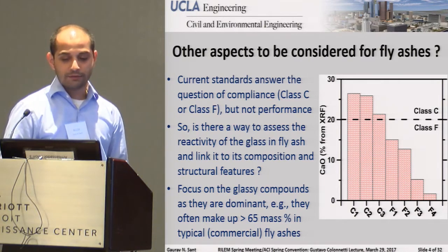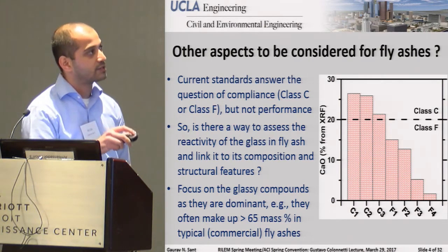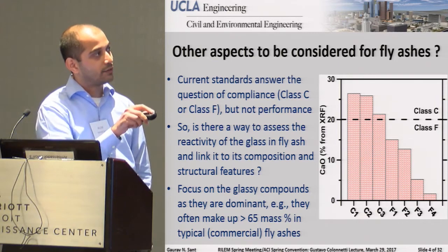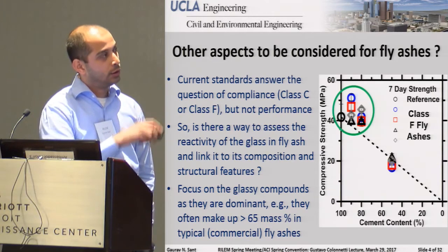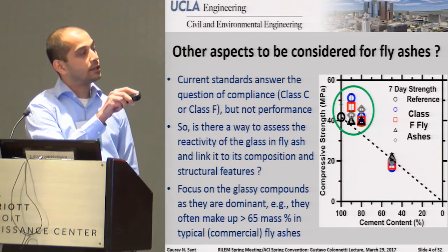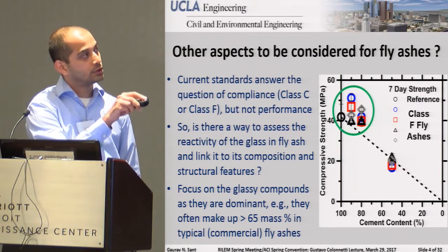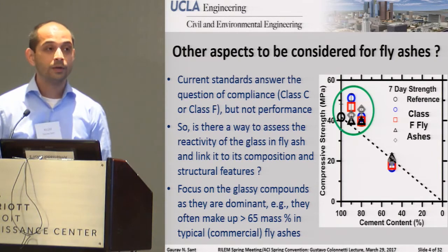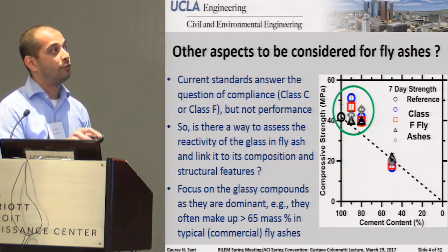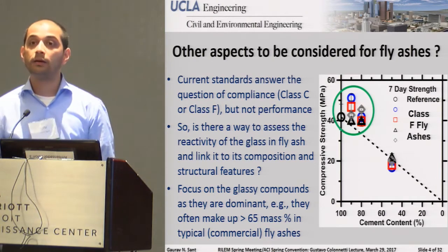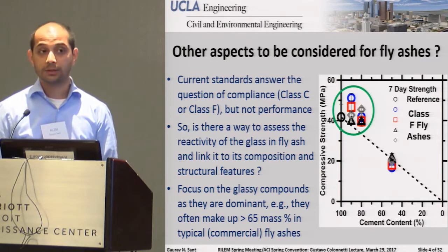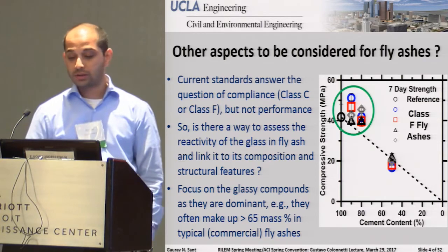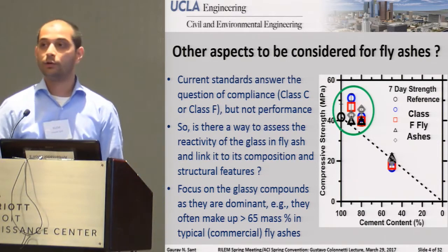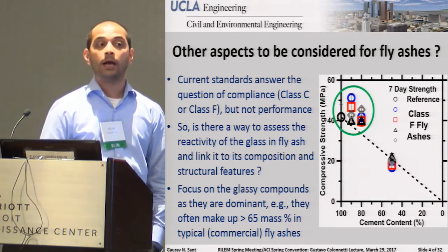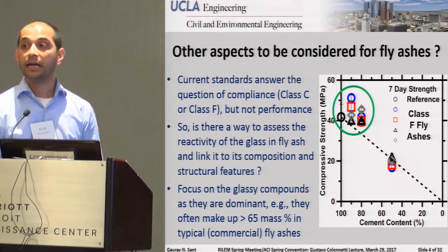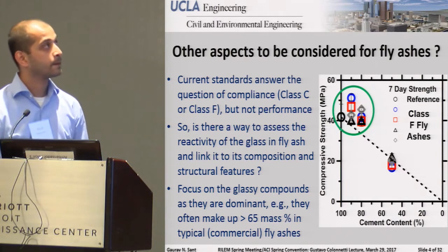And when you look at the effects on performance, for example, this is just an example of 7-day strength, but these are all Class F fly ashes going from the blue circle to the gray diamond. And you can see that starting right at even 7 days, there is a clear difference in how they all behave. So there's really a question of why. Now, if you go from 7 days to a later period in time, you see that these differences continue to persist. And so it becomes quite important to consider, well, why do different fly ashes show different reactivity? And how do you rank, assess and identify reactivity quantitatively?